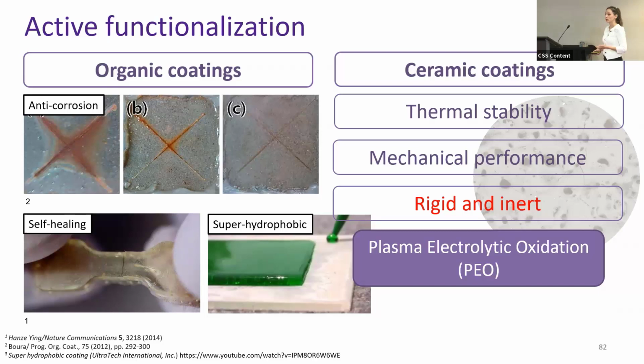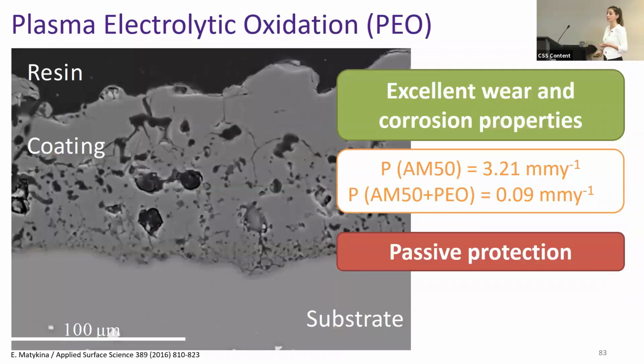There are different coating technologies used to manufacture ceramic coatings, but for this work we have selected plasma electrolytic oxidation, also known as PEO. This technique is becoming quite popular because it's very versatile, it's environmentally friendly, and it can be used to coat components with complex geometries, such as the ones manufactured by 3D printing. We can improve quite considerably the corrosion and wear response of light alloys with this technology, but the main problem is that they only offer passive protection. That is, once they break, they no longer protect the material underneath, and corrosion will propagate catastrophically throughout the metal.